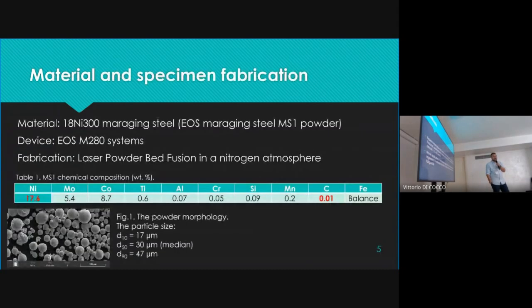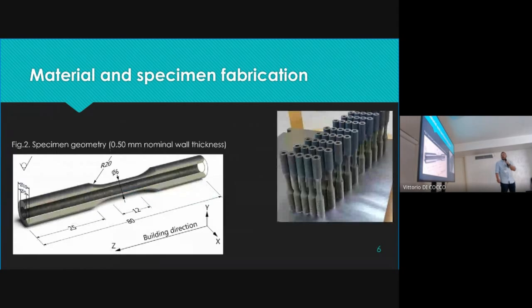So to shortly characterize the material, we use the EOS maraging steel. The company's name for this powder is MS1. And we use the 3D printer, an EOS M280. It's laser powder bed fusion, and it was done in nitrogen atmosphere. The powder morphology is at the bottom of the slide. The specimens we used were hollow, with a wall thickness nominally 0.5 millimeter, and they were all printed in the vertical direction.